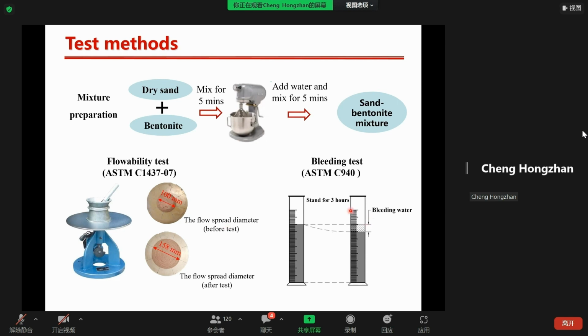On the other hand, the bleeding test used a 1,000 millilitre cylinder, and the volume of bleeding water was recorded at 3 hours standing. The bleeding ratio was defined as the ratio between the volume of bleeding water and the initial volume of water in the cylinder.